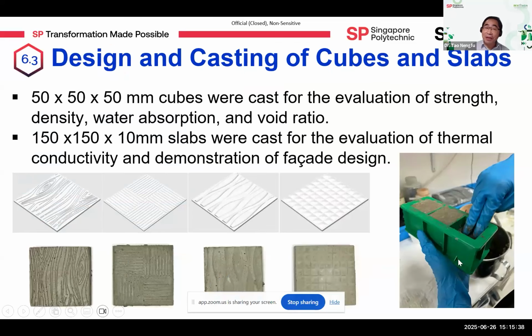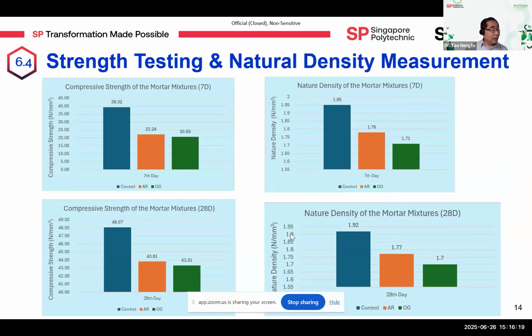50 by 50 by 50 mm cubes using this mold were cast for the evaluation of strength, density, water absorption, and void ratio. 150 by 150 slabs were cast for evaluation of the thermal conductivity and demonstration of facade design. From the photo here, you can see that the slabs have good surface quality and demonstrate the design details.